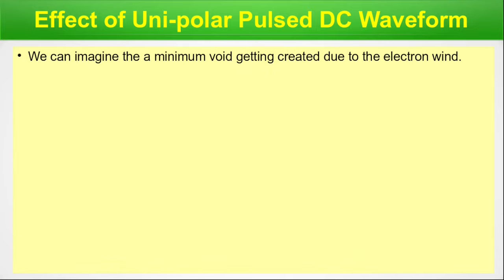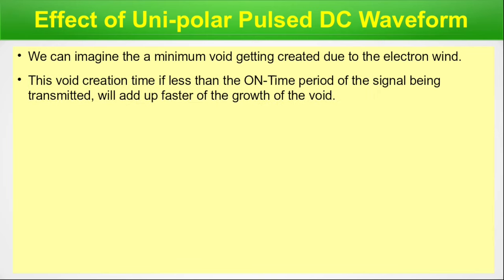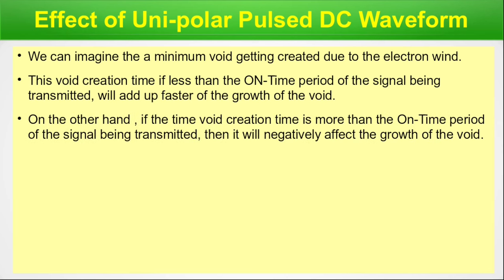Effect of the unipolar pulsed DC waveform. We can imagine the minimum void getting created due to the electron wind. This void creation time is less than the on-time period of the signal being transmitted. This adds up to faster growth of the void. Now folks, please remember we are talking about AC, so there will be an on period and there will be an off period because this is a unipolar pulsed DC waveform. On the other hand, if the time of void creation is more than the on-time period of the signal being transmitted, then it will negatively affect the growth of the void. Negatively affects means that it will reduce the growth, or the rate of growth will be less than in the previous condition.